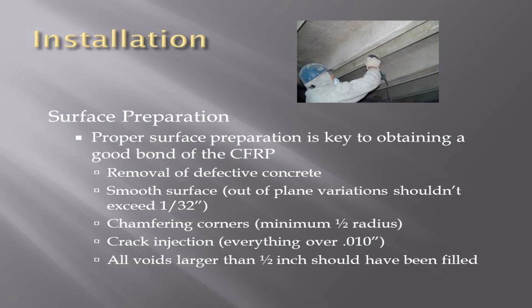You need to chamfer corners. I know we have several of our FRP jobs where the corners weren't chamfered. You need a round corner so the U-wrap can actually transfer stress between the sides and the bottom. A minimum of half-inch radius is recommended.